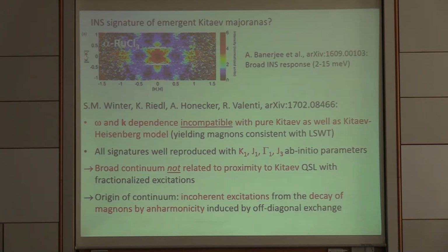But now again, the ab initio work by Roser Valenti's group showed that the omega and Q dependence of this excitation is actually incompatible with what would have been expected for the pure Kitaev model. And it's also inconsistent with what would have been expected for the Kitaev-Heisenberg model discussed originally for alpha ruthenium trichloride, since that would just give magnons consistent with linear spin wave theory. Instead, all these signatures observed in the experiment are well reproduced with the ab initio parameters for K1, J1, and the off-diagonal exchange gamma1 plus J3, which I just mentioned on the previous slide.